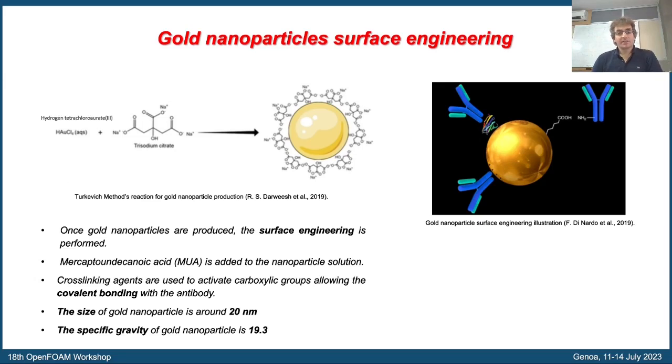The diagnostic technique consists in a combination of two techniques actually. First of all, gold nanoparticles are delivered by injection in the blood circulation. Each golden nanoparticle is engineered by mounting pieces of antibodies at each particle surface, and this antibody will stick onto its own antigen, which is actually produced by atherosclerotic plaques. So the golden nanoparticle will stick onto atherosclerotic plaques because of this antibody.